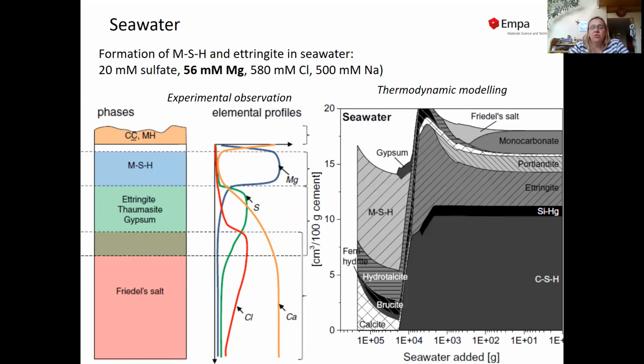We can do modeling again, and it looks similar to what we've seen before. We have the unhydrated sample here. If we equilibrate it with more and more seawater, we first predict the Friedel's salt formation, in agreement with the observation plotted here. Then we predict the formation of more ettringite, and in the outermost layer, we predict the formation of M-S-H as well as of brucite and calcite.